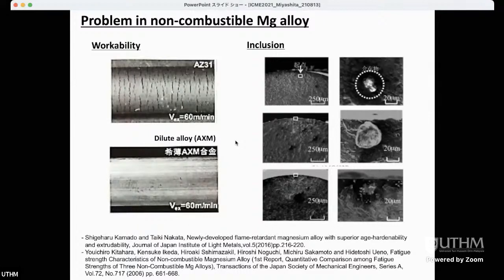However, as I already mentioned in the introduction, mechanical property depends on the alloy element. So if we reduce the alloy element, basically mechanical property also decreases. So we needed to make a balance between mechanical property and workability, I mean the extrusion ability. Another problem, which I already introduced, is that in some cases we can observe the inclusion at the fracture origin. In this paper, they observed calcium oxide at the fracture origin as an inclusion.